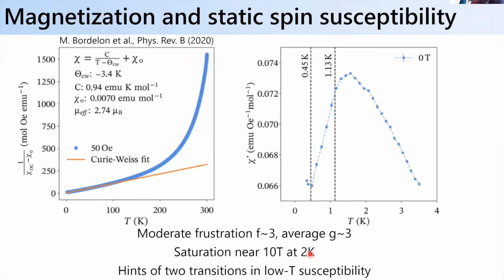So for this system, then we can look at the magnetization. All right, so the susceptibility. And this is the inverse susceptibility. And again, we have to fit at low temperatures to get away from the thermally excited crystal field. But when we do so, we get an antiferromagnetic exchange interaction around -3 Kelvin. If you look at even lower temperatures, then what you find is that there's this cusp here where it freezes out, where you start to see the susceptibility turn over. And then at the very bottom end, you see there's sort of this turnover here. Okay, so this data doesn't get low enough to really show much about this, but it suggests there might be something else going on at around 450 millikelvin.